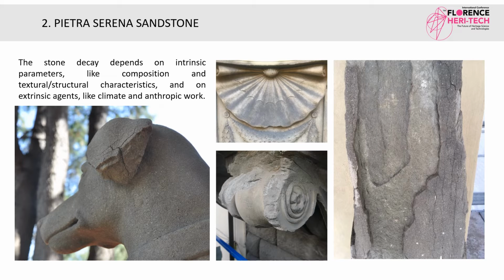Water, like rainwater and air humidity, plays a fundamental role in Pietra Serena decay, producing volumetric expansion of the clay minerals and the matrix, removing the clay minerals and causing consequent decohesion of grains, exfoliation up to contour scaling and material detachment. And again, water acts by dissolving the calcite cement, increasing the stone porosity, with formation of crusts on the external surface during the precipitation phase of calcite.